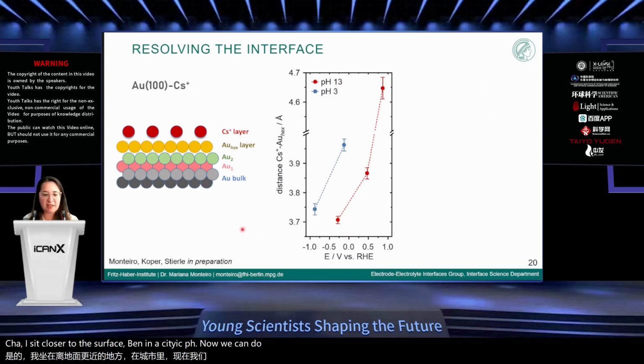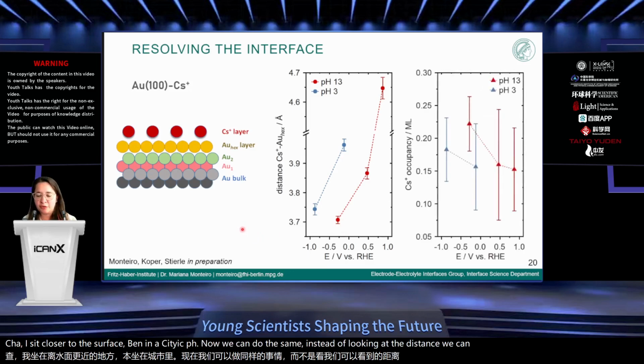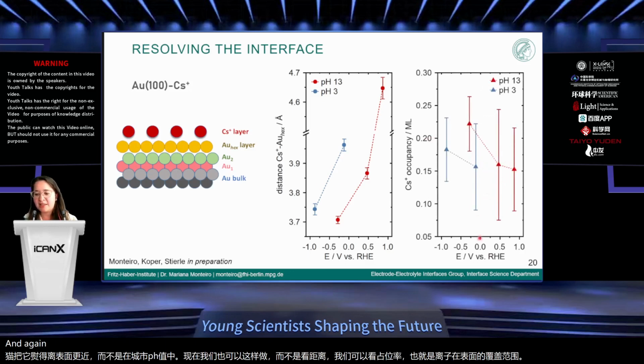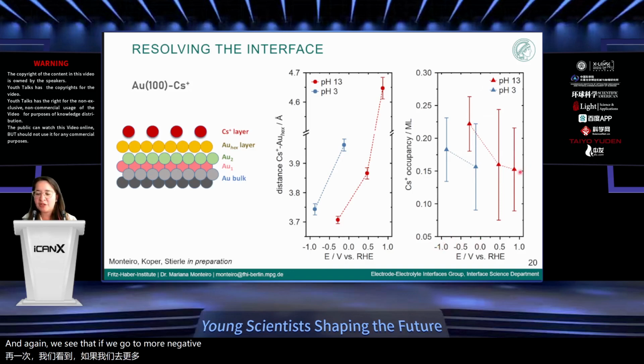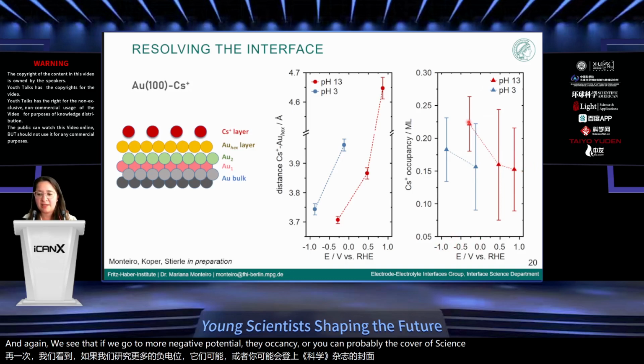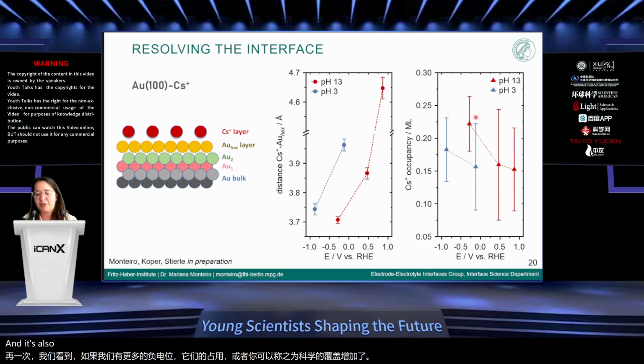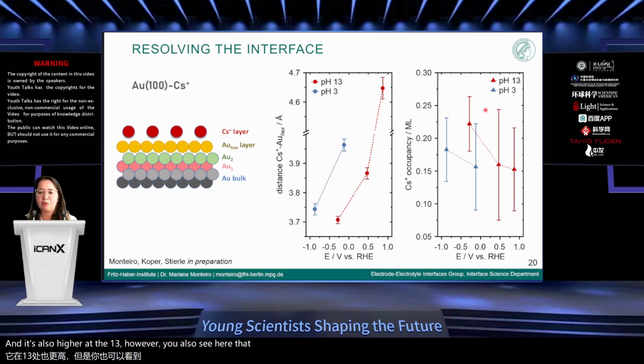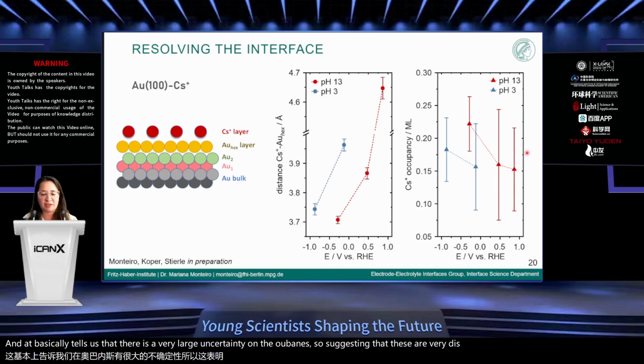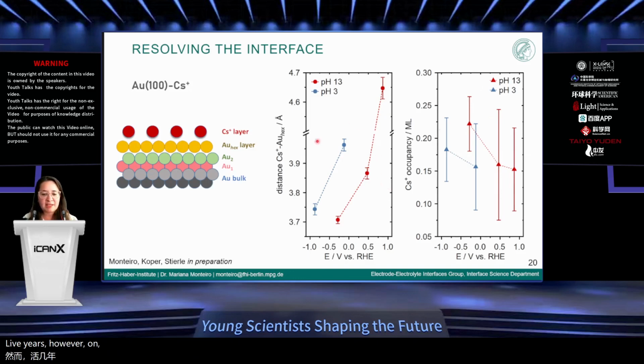Now we can do the same, and instead of looking at the distance, we can look at the occupancy, so the coverage of ions on the surface. And again, we see that if we go to more negative potentials, the occupancy, or you can call it the coverage of ions, increases, and it's also higher at pH 13. However, you also see here that the error bars on the occupancy are very large, and that basically tells us that there is a very large uncertainty on the occupancy, suggesting that these are very disordered layers. However, on the distance, we have a very good precision.